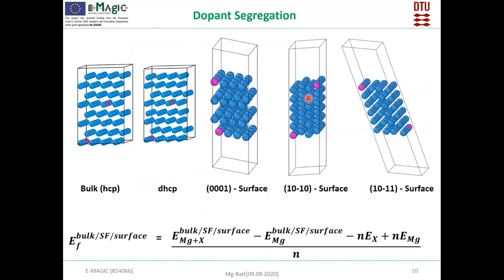So in the DFT calculation, we normally put a vacuum to mimic the surfaces. And we put 2 dopants on each of the surfaces. And then we calculate the energy of formation of all the structures. So the energy of formation with the dopant either in bulk or in stacking fault or in any of the surfaces, using this equation.